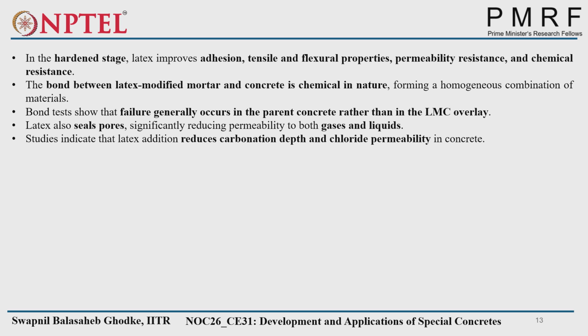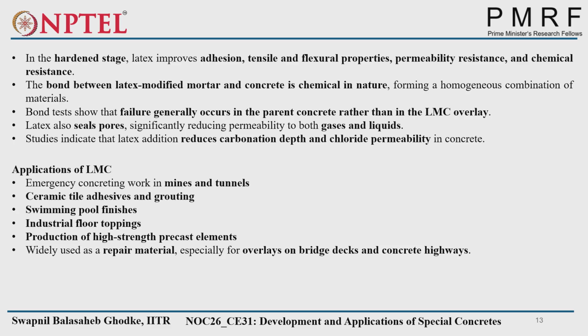Latex also seals pores, significantly reducing permeability to both gases and liquids. Also, studies indicate that it reduces carbonation depth and chloride permeability. Obviously, as we are reducing the pores, any type of hazardous material will not get into the pores. That's why, because of this, there is no CO2 ingress and no chloride penetration. That's why there is better durability. So, where can we use this type of concrete?